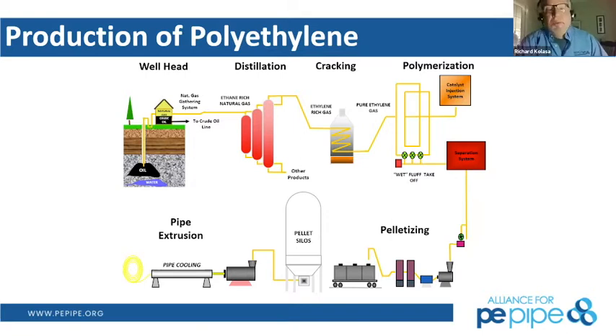Then we purify that gas, that ethylene, into a double carbon with 4 hydrogen type component. Then we inject the catalyst system into it to open up that double bond between the carbons to create these long chains of polymer. When you open up that center bond, you create a free radical. So we control in the reaction system how long we make those chains, and that's referred to as the distribution of the polymer. For pipe products, they have a specific molecular weight that we want to accomplish, and also a range of distribution of those lengths, so we can obtain the performance that we want for water and sewer applications and pressurized systems.